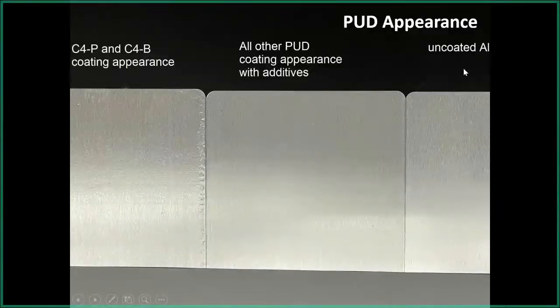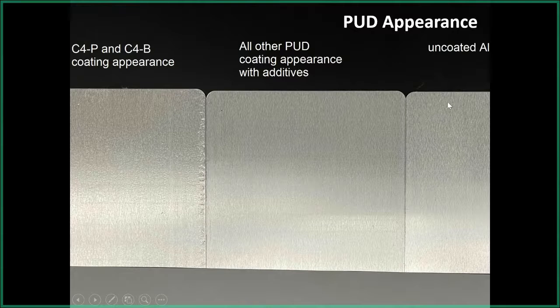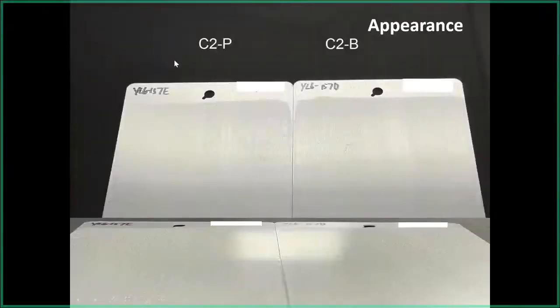Let me just show you that. For some reason, we have a picture of uncoated aluminum, but this is typical of all but one of the additives here. So they all gave really nice flow and leveling. The C4 additive did not give very good flow and leveling, but it looks the same for the C4 petroleum and bio-based. So since we're looking for differences between P and B, we're basically just seeing them behave the same. And just to perform a comparison here, the C2P and C2B, this is a composite photo of the same drawdowns, just at different angles. You can see really they look identical.